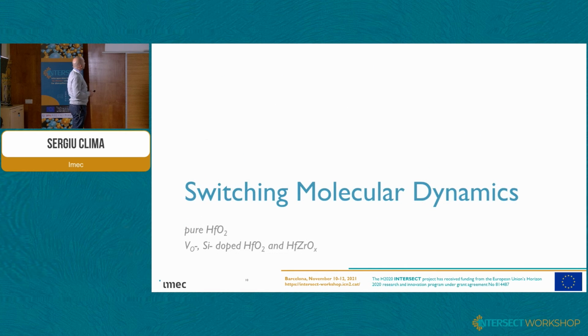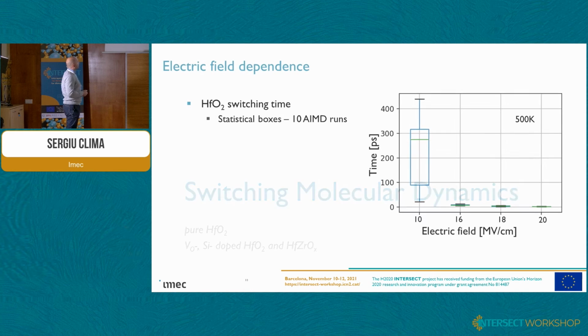Well, so choosing one of those two mechanisms, we look more into the dynamics of the switching. So we do over and over different models, different ab initio molecular dynamics, and we calculate how long it takes for the switching to start. So basically, we look at the nucleation times. Each of those statistical boxes is in the range of 9 to 10 ab initio molecular dynamics runs, and all this for different electric fields.